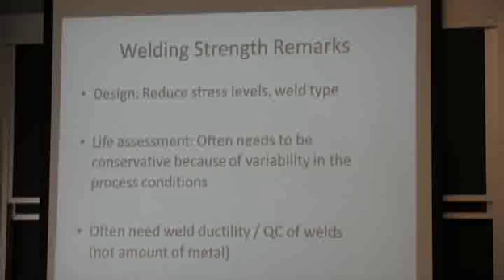Sometimes it's because of buckling resistance. That's why you have bigger pieces. So we really talked about, in details, trying to reduce the loads on welds, and selecting weld type, whether it's a groove or fillet, the orientation, to also help yourself. You have to be conservative if you're going to have cyclic loads. And as far as the execution and the quality control, be aware that welding is one of those things that is very user sensitive. And you have to put a criteria if you're designing it. If you own it, you want to have some form of inspection or control to make sure that you keep getting the quality that you expected to begin with.